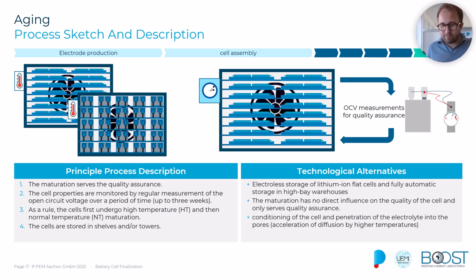Then in the high temperature aging, we would first store the cells at a higher temperature, for example, around 40, 50 degrees for some days, because the heat might accelerate certain side reactions and electrolyte wetting of any remaining dry pores inside of the battery cell. So it would help the electrolyte penetration and speed up the initial degradation that might happen, effectively burning in the cell. Higher temperature accelerates the diffusion of the electrolytes. That typically might take a few days to a week, around 45 degrees temperature.